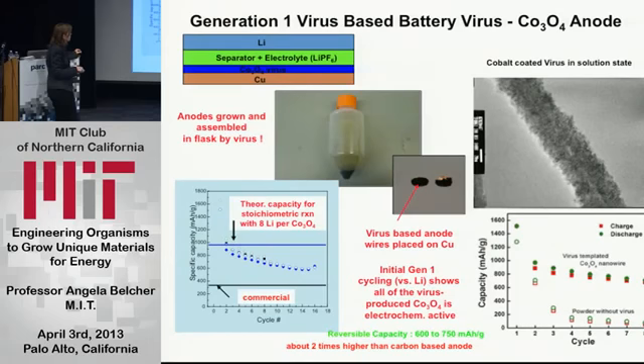And if you say, well, how does it compare to, this is all made at room temperature, how does it compare to making just cobalt oxide nanoparticles by itself at room temperature, and that's what it looks like here. It basically is not a very good battery electrode material at all. And so the virus really is doing something, making it more crystalline, controlling the crystal structure, organizing in a way that you get increased performance.